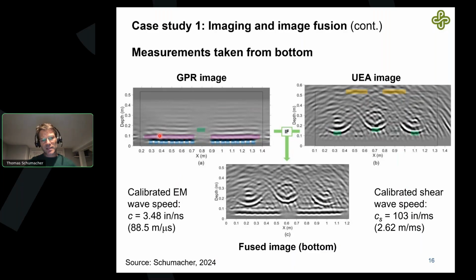There's a bunch of additional bands that you see here. They are really multiple reflections that are not real. They're just caused because you have a very dense first layer of bars. You send that electromagnetic wave in, and that wave now bounces back and forth. And that causes these, what we call multiples, to occur.